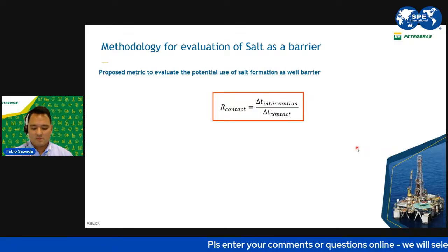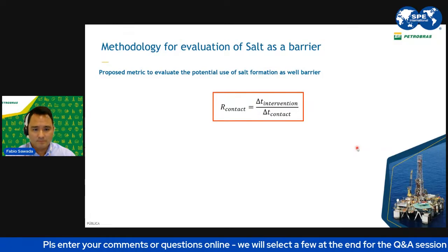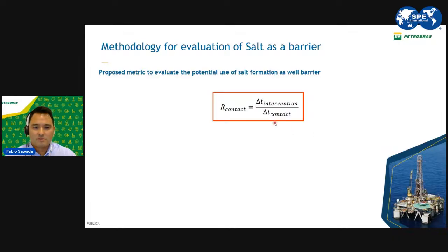Using the same assumptions, we created a metric, kind of a ratio, to see if the salt formation has the potential of creeping in and forming the barrier. We are comparing the time of a certain intervention of the well, I mean, from well construction to the first heavy workover that we would have in the well. This would be the intervention time, and for the contact, it would be the time that we expect the salt to touch the casing outer diameter. So this ratio could bring us a decision-making parameter, so we can decide if we can run a log to see if the salt is really touching the casing.